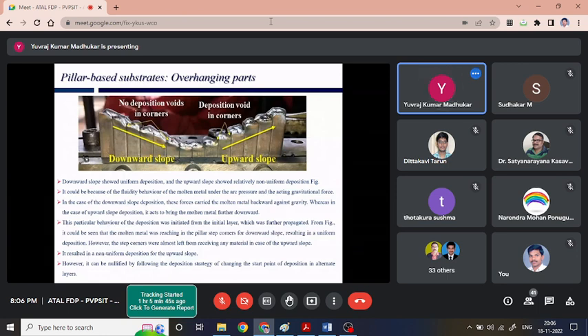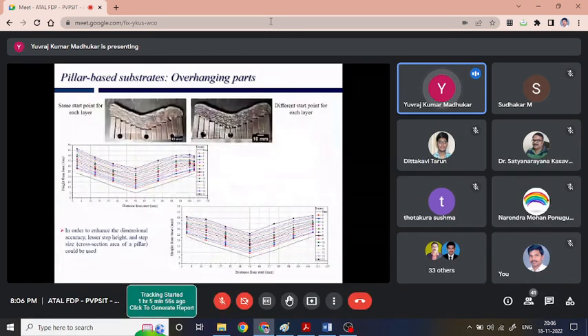So here we could see at the beginning there might be some issues with the deposition. However, with the optimization of parameters, as the number of layers increases, we could achieve the best deposition like this, no problem at all. So certainly we could deposit it. That means by changing the pillar heights, we could deposit the overhang features without the use of any additional axis of motion, as we did in the case of making a propeller. By changing this pillar height, we can deposit the overhang features. Yes, of course, we have to machine it for its separation.